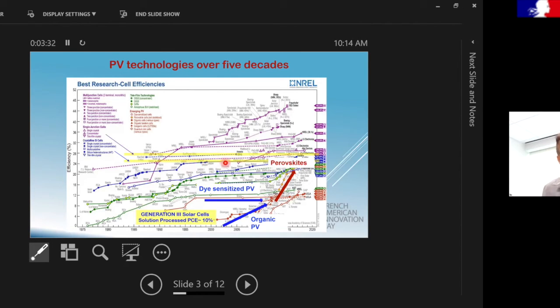And then, of course, you have silicon, which we find on roofs every day, and they are at about 25%. Now, there's this concept of generation 3 solar cells, which refers specifically to materials where you can put them in solutions, do dirty chemistry, and spin them using different methods on any surface and create photovoltaic devices like that. Some of the examples were dye-sensitized solar cells or organic solar cells. And you see that over 30 years, these efficiencies never really went beyond 10%.